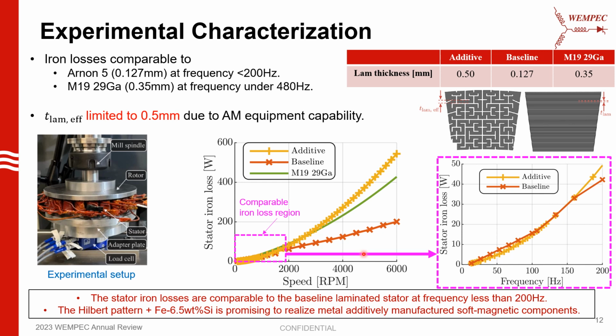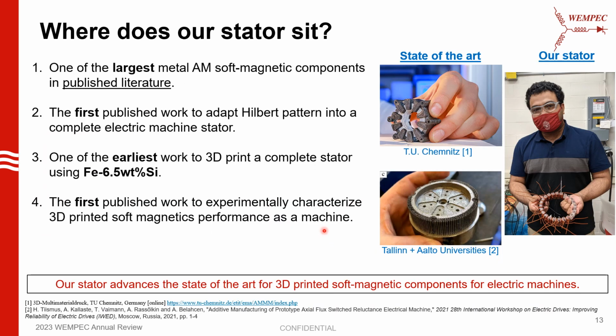If we just look at M1929 gauge and the additive stators, we can see that the losses are comparable up to a frequency of 480 Hz, which is even higher. So based on all of this, where does our stator sit?